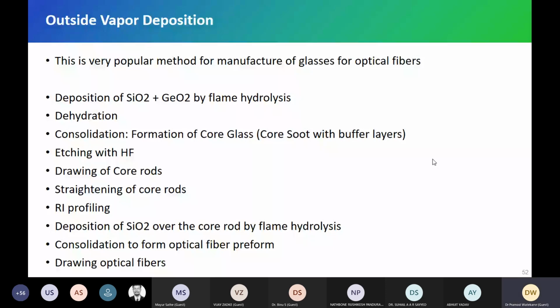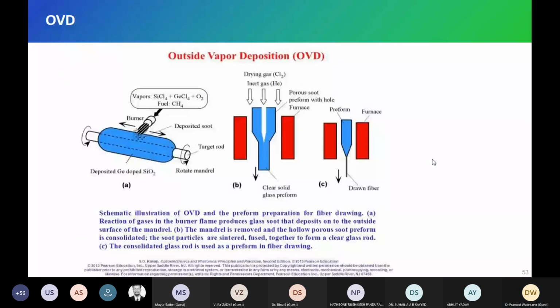This I will explain here, how it looks like. So we have this target rod. Generally we take a graphite rod. Some companies use a glass rod, but it can be brittle. So we take the graphite rod here. It is very strong. And over this now we deposit some layer, right? We have a burner here and we deposit the soot. We don't get glass now. We deposit the soot, white colored soot. I'll show you the picture. So we keep the temperature lower so that the soot is deposited here.